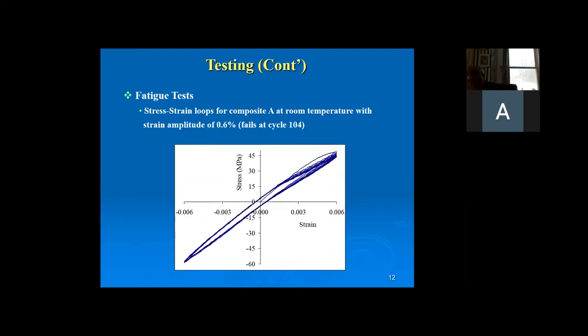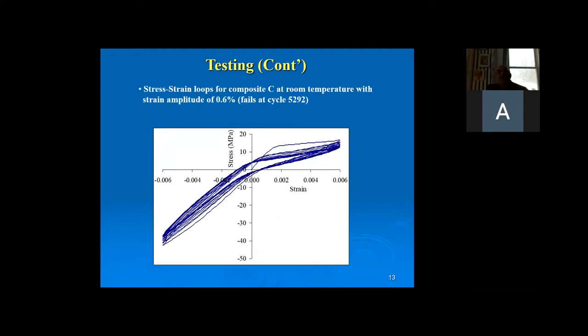Now, and then we run fatigue test, tension compression fatigue test in these samples. Again, we have A, B, C samples. And then we run them at different temperatures. At room temperature, when the strain amplitude is 0.6%, it fails in 10^4 cycles. And then we test composite C at room temperature. Remember, composite C, there's a debonding agent between the filler and the matrix. So fillers are just floating inside the matrix. So you are getting pretty much in the tension zone the response of the polymer, right?